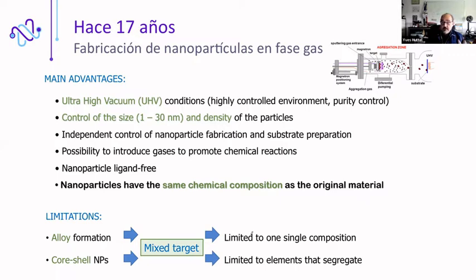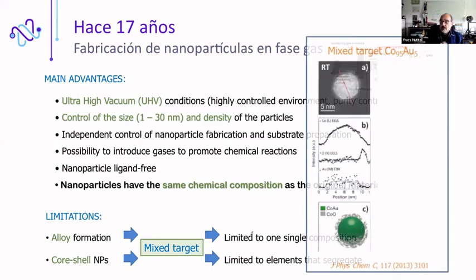The other limitation is that every time you want to change the chemical composition of your nanoparticles, you have to open the system and replace the target inside the magnetron. And as you remember, we are working in ultra high vacuum conditions, which means that after changing the target, you have to pump down the whole system to reach again the vacuum or ultra high vacuum conditions, which can take several days. So it is not very easy to change a target or change the chemical composition. Anyway, we were quite happy. We bought a commercial cluster source, and we started to make fundamental studies.